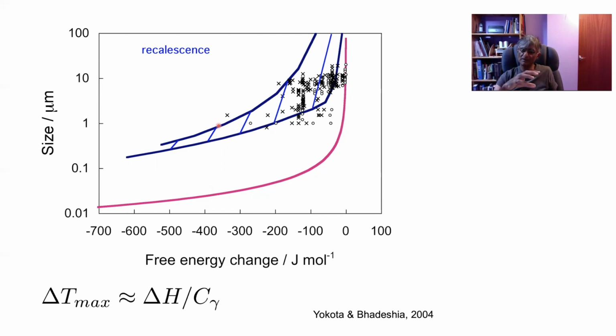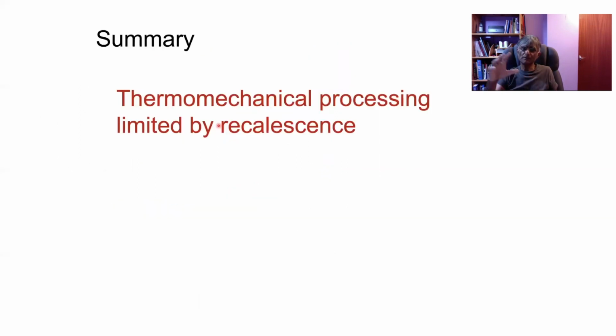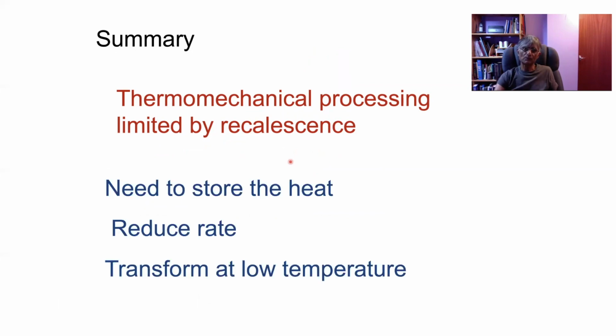This enthalpy release is known as recalescence. It heats up your material simply from the enthalpy change of transformation. So in summary, thermomechanical processing is limited by this recalescence, the release of the enthalpy of transformation. So we need to do something to help. We need some mechanism of storing the heat inside the material, okay?